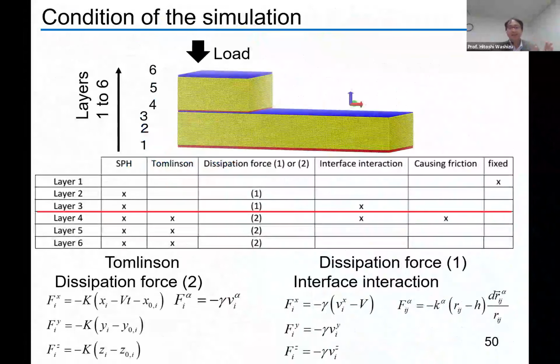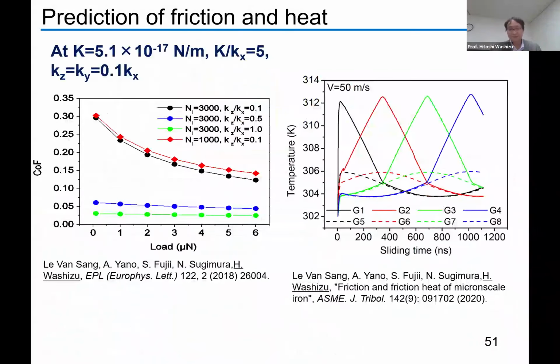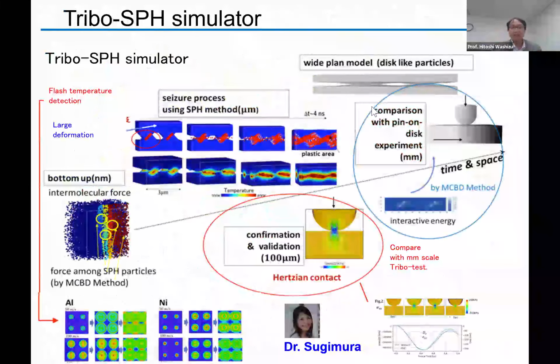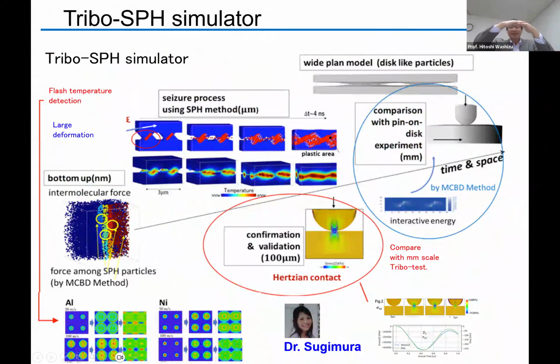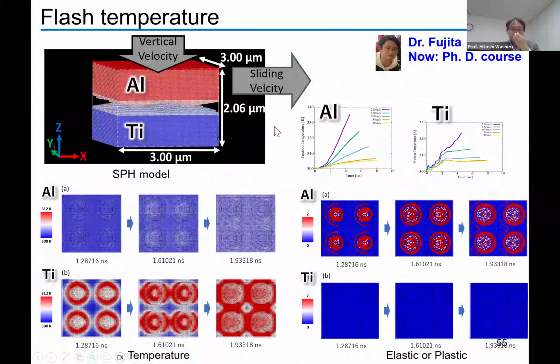Okay, so in this simulation, we only use elastic interaction. But many materials have elastic-plastic interaction. So in heavy conditions, they move not only in the elastic regime but into the plastic condition, and then the surface structure changes, and then friction occurs. So Dr. Sugimura made a bottom-up concept to simulate, including the elastic-plastic information, for this kind of SPH particle. So this is one feature. And then here shows the temperature difference.